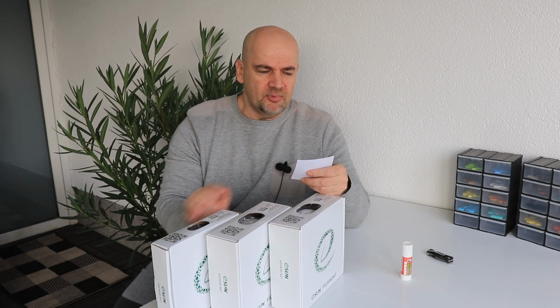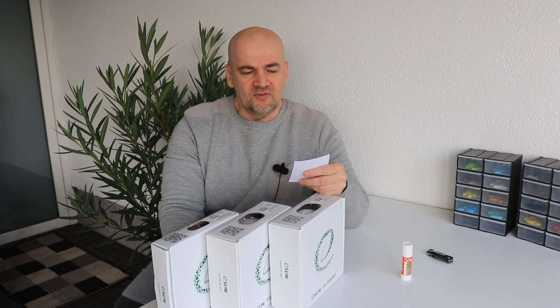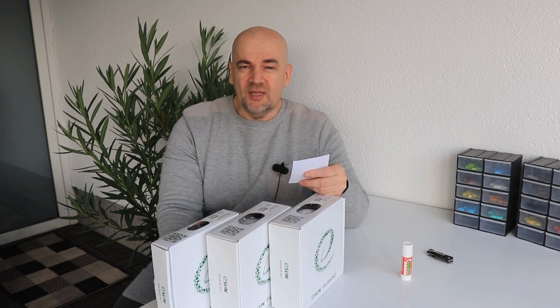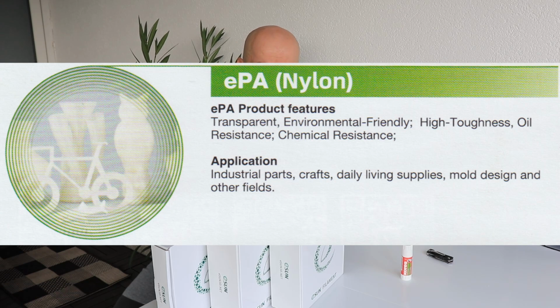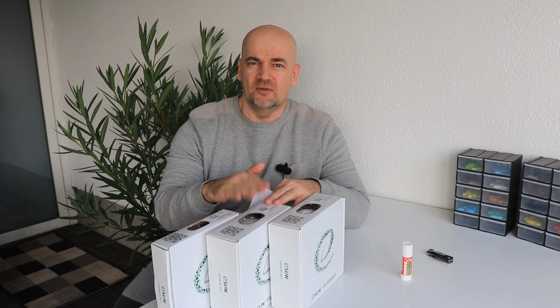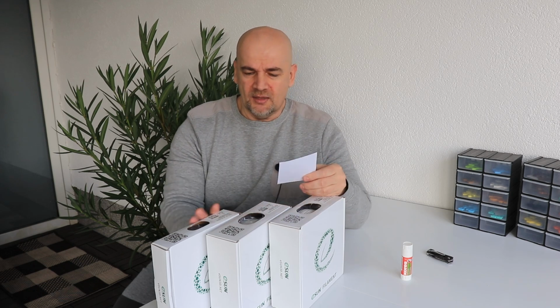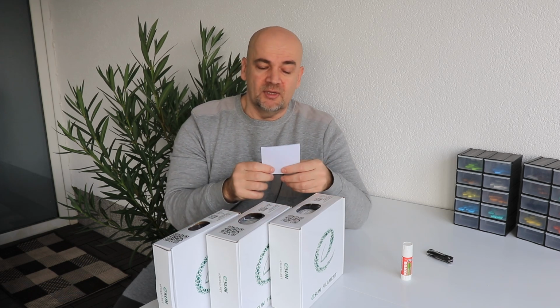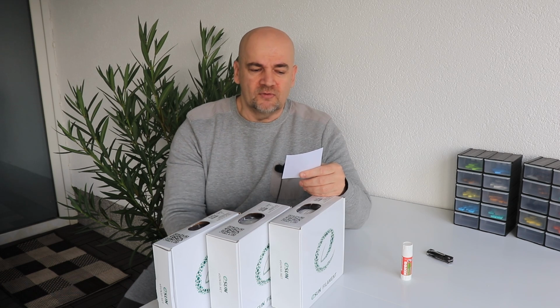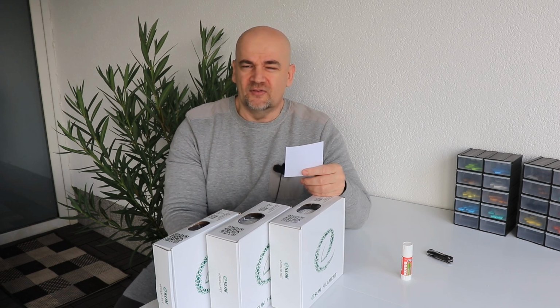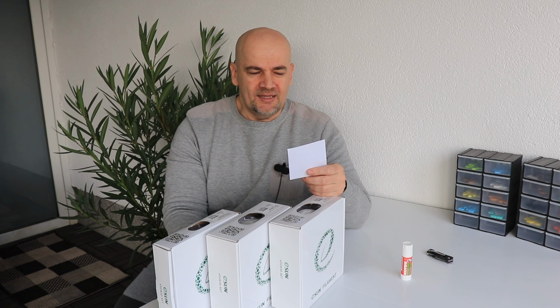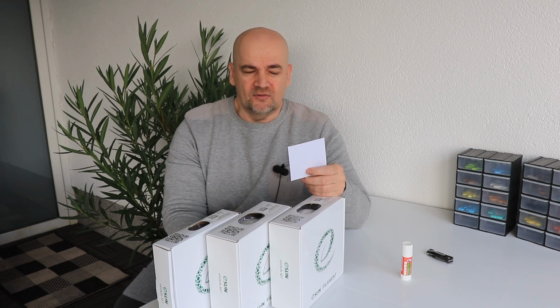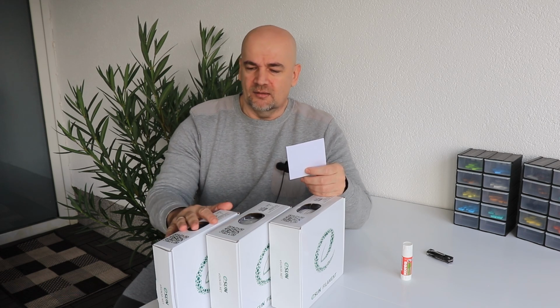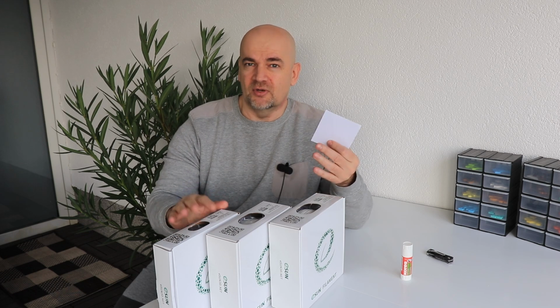For the nylon, the printing temperature is between 230 and 260 degrees Celsius. The bed temperature is between 80 and 90 degrees Celsius. High toughness, oil and chemical resistance, and as I mentioned, it has to be dried. And for the polycarbonate, the printing temperature is even higher, 235 to 260 degrees Celsius for the nozzle, and 80 to 110 degrees Celsius for the bed, and it is temperature resistant.